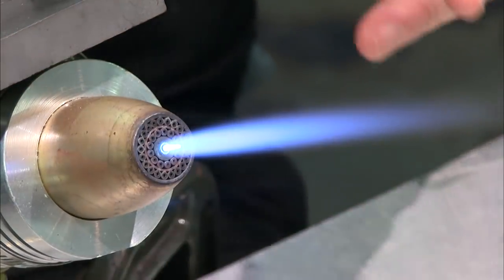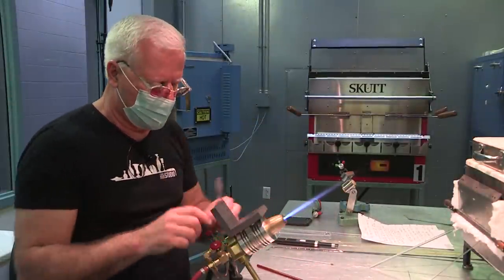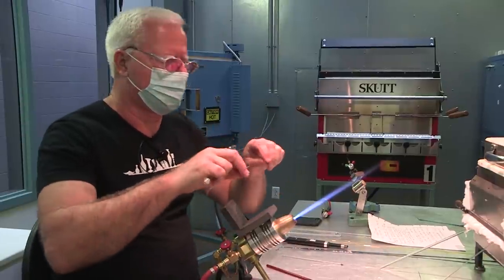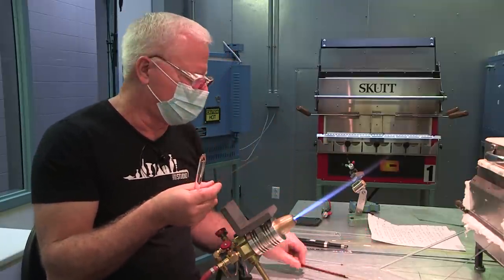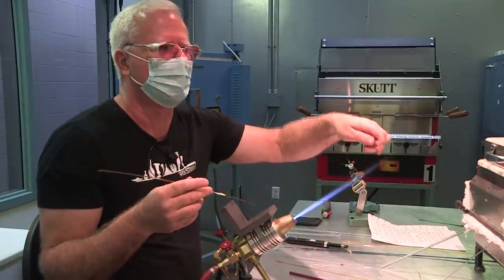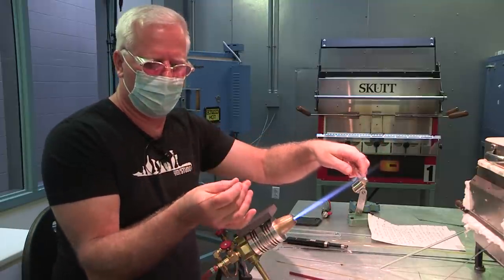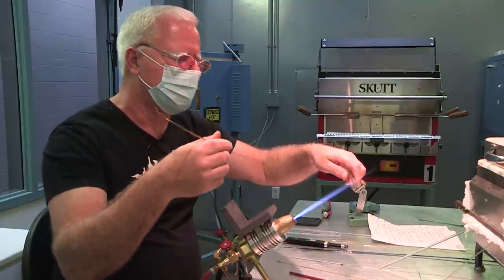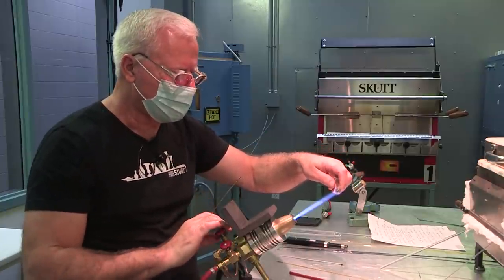It's simply an amber color that I've also pulled into a stringer that I'm going to use to create my acorn. And the reason I'm doing this, I'm going to do it with a clear glass, and I'm going to overlay an amber stringer over the top. And I do this for two reasons. Number one, if I just condensed this amber down and made it into a sphere to make that acorn, it would be incredibly dark. So much so that it would be almost ominous and not inviting to look at, in my opinion. So I don't do that. I will string this amber that I've pulled very thinly into the stringer onto clear, because the clear will be a much larger base, and then it'll be transparent as well, so any light that passes through will just pass through the amber stringer, and it'll look much lighter.